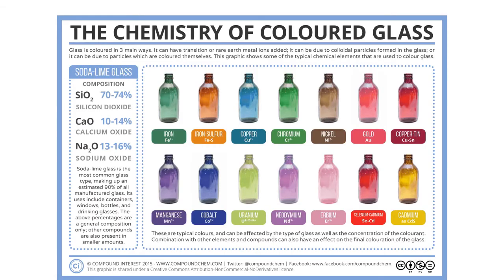So glass can be a lot of different colors depending on which of these transition metals are added to a piece. This is just a graphic I found of some different color combinations. And you can see how iron on its own gives us this emerald green color, but when mixed with sulfur, we get more of an iron brown rusty color. Chromium in the scenario seen here gives green, but chromium can also be red if put in combination with other elements and heated to the right conditions.